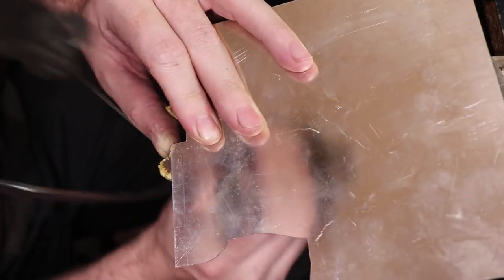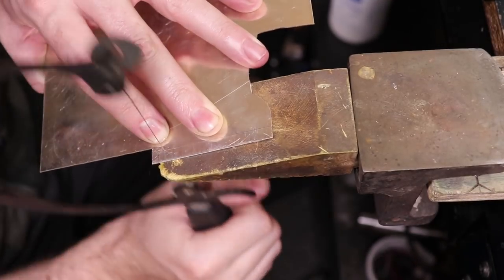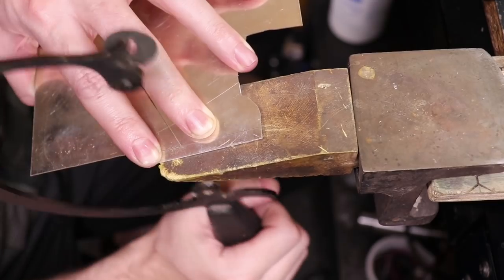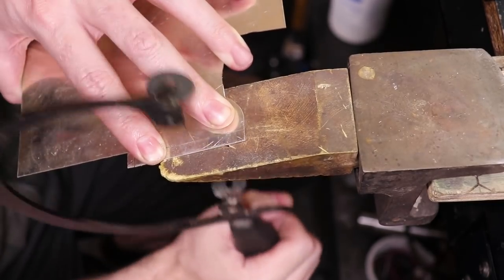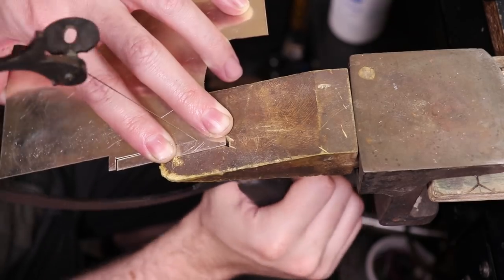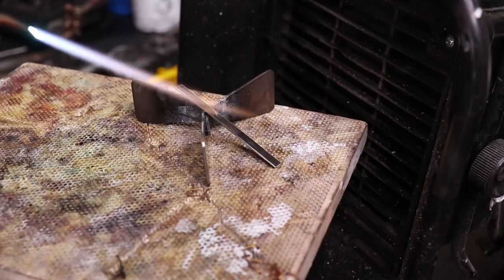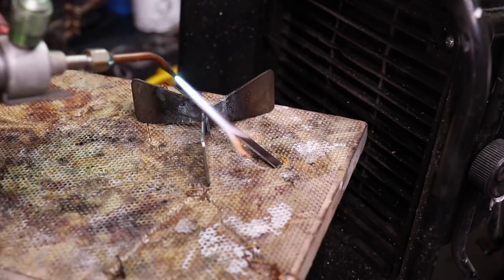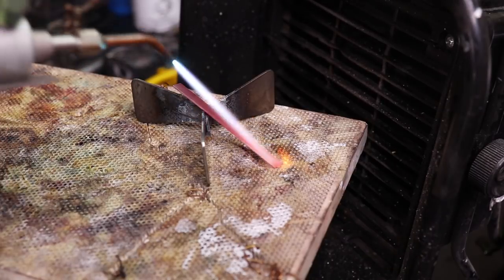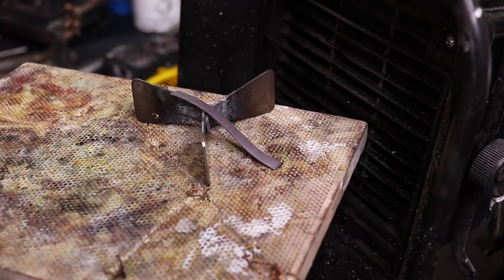As I'm waiting for that to clean up, I'm going to cut out the outside of the container area of the ring from this sheet of silver, and this is about 0.6 millimeters thick. Before we can actually form this into the shape I need, I need to anneal it to soften the metal. So I'm going to do that by heating it up with my torch, and then I'm going to have to pickle this afterwards.